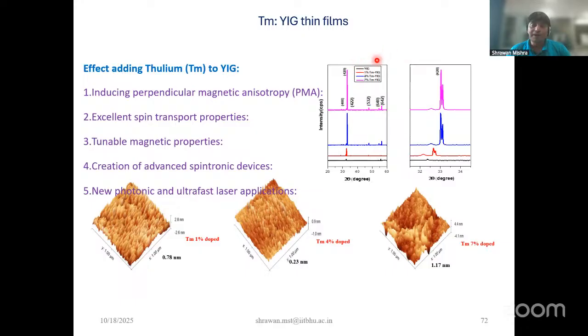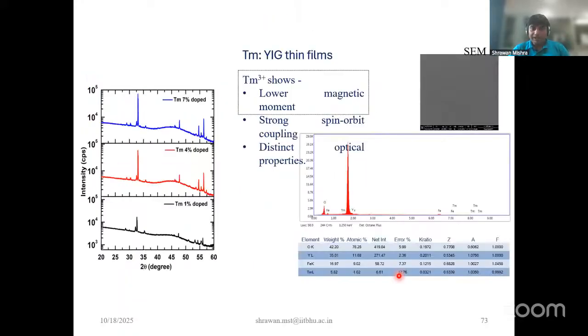So we compare our undoped garnet with the 1% doped, 4% and 7% doped garnet. And this is the AFM image. When we dope the thulium, you can see the modulation in the microstructure. It's very, very pronounced. And all the doped samples still obey the garnet structure, as shown in this X-ray diffraction data. So this is, again, more detail about the structural property.